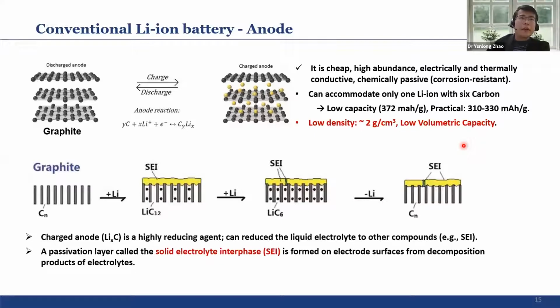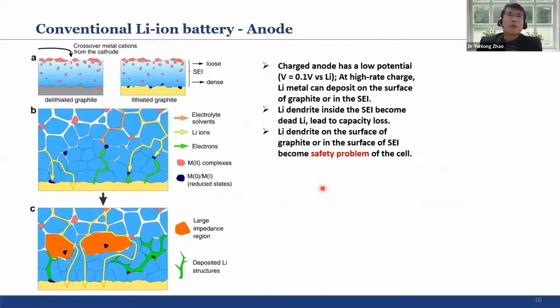Before explaining another limitation, let me first explain what the solid electrolyte interphase means. When we charge the battery, as shown in the previous slides, the lithium will diffuse into the carbon, and this becomes lithiated carbon. This is a highly reducing agent. It can reduce some of the liquid electrolyte into other components, for example some solid components, and these can attach to the surface of the anode. We call this layer the solid electrolyte interphase, or SEI for short. It can protect against some corrosion reactions.